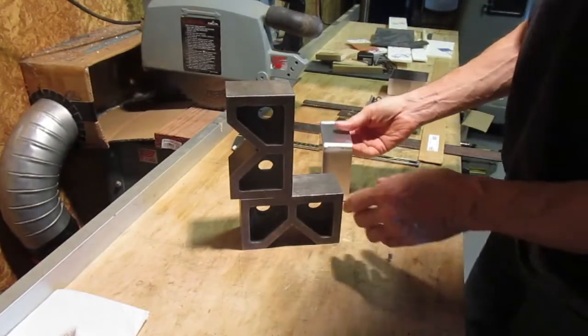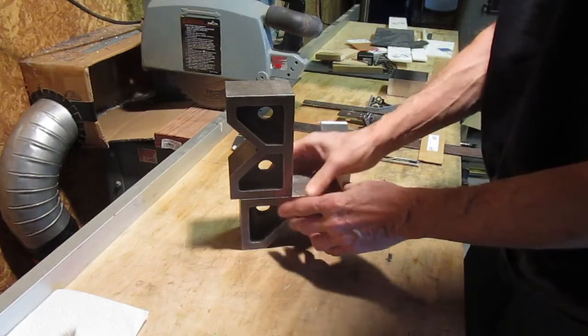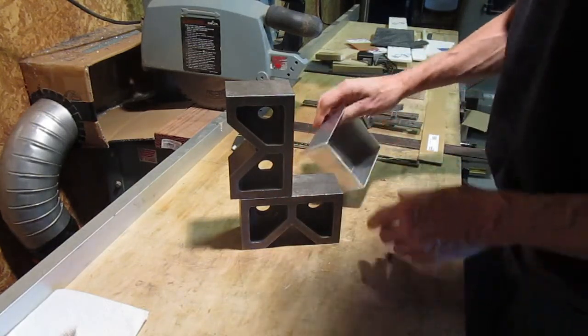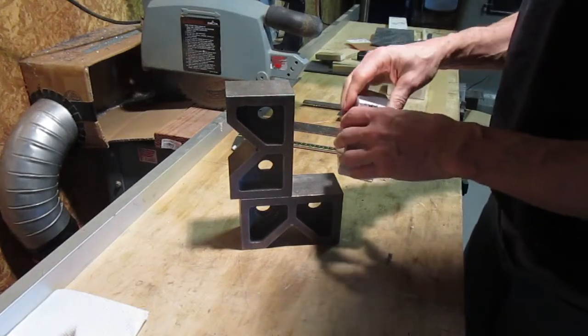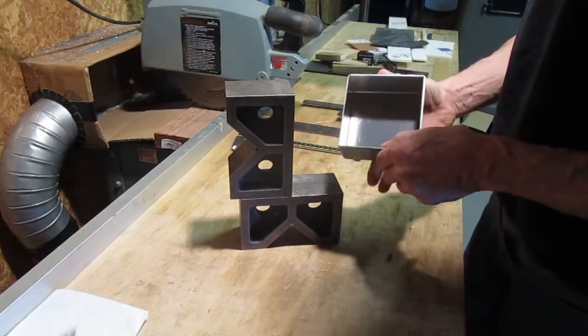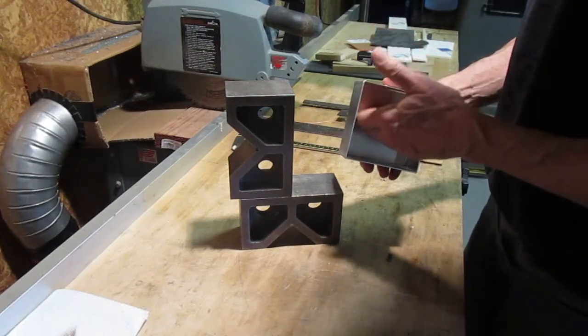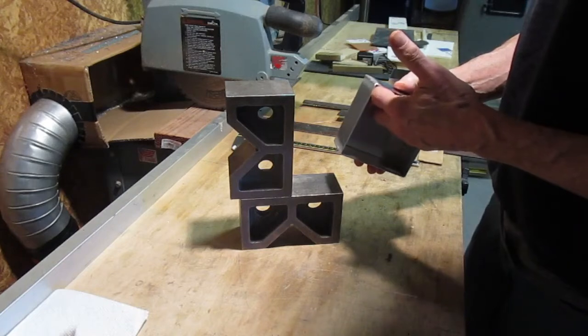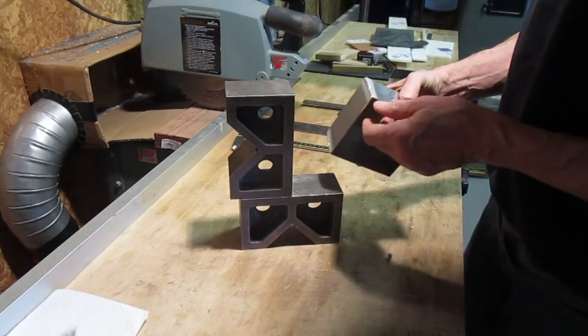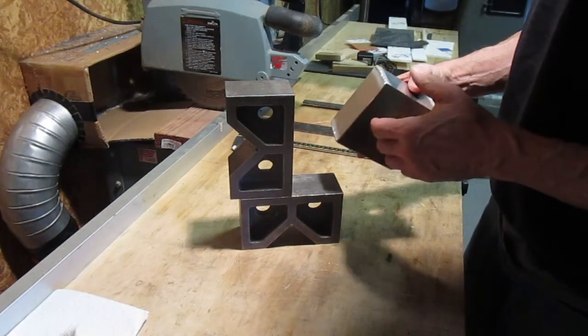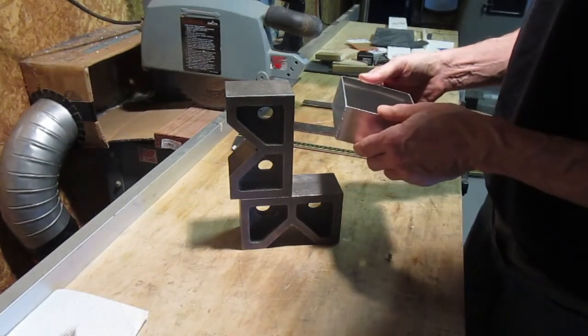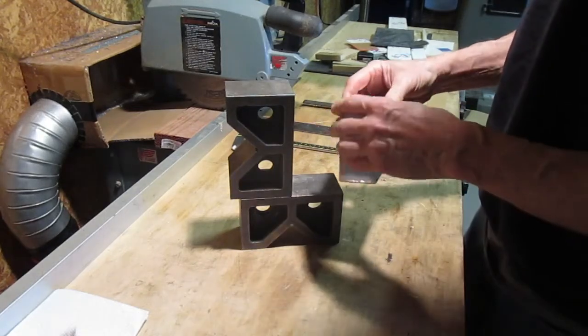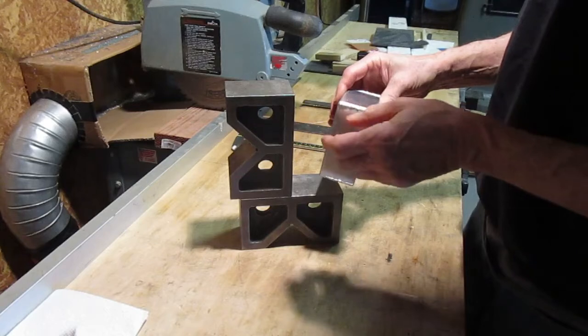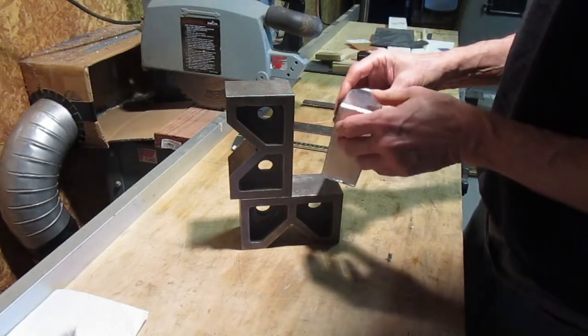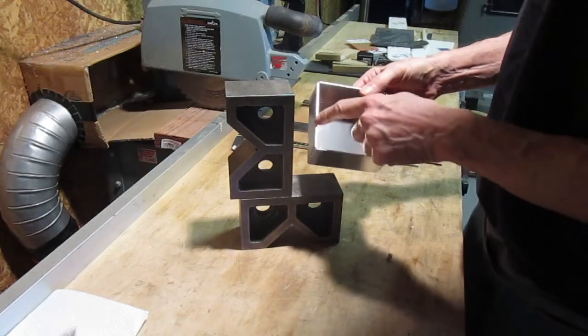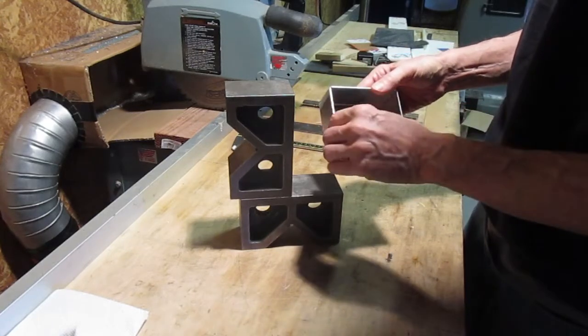Okay, let's see how we did. If you have a set of precision V blocks, you can create a right angle reference here. So we welded 4 corners of this box. They were open. As I had mentioned, we used a piece of extruded aluminum right angle to form these bends and also act as a heat sink while we were doing the welding, so the metal doesn't run away. But what happens with aluminum, since it has a high coefficient of thermal expansion, when the weld is finished, the metal shrinks and it creates distortion and stresses. So these edges here, you probably can't see, but they're pulled in slightly.